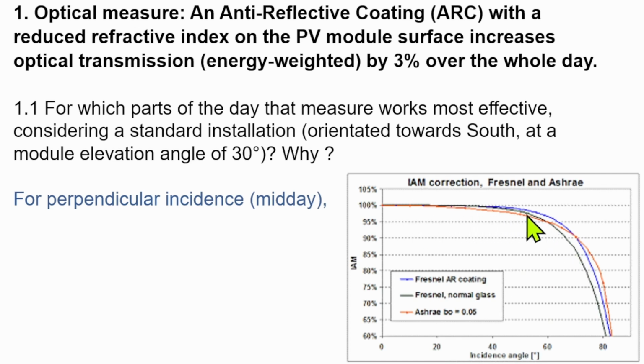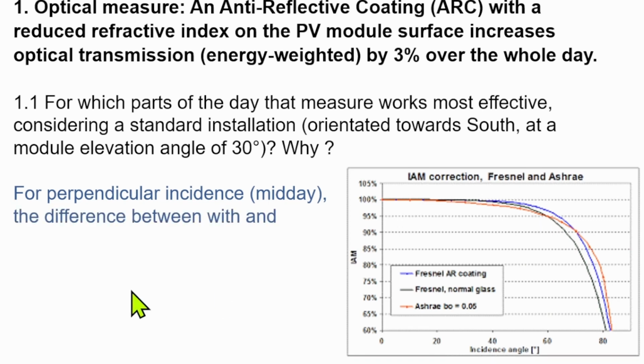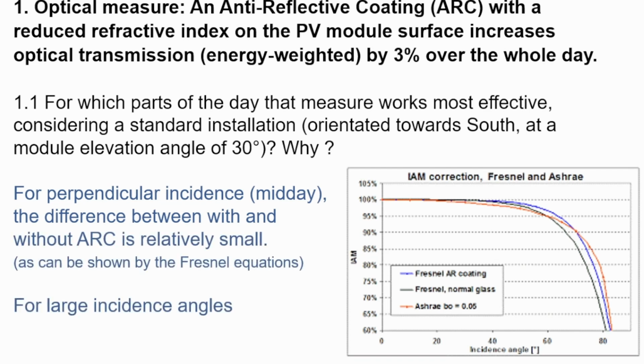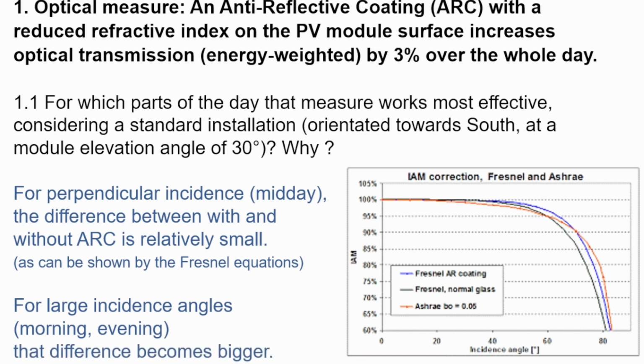So here you see the effect of the anti-reflective coating. So you don't see such a big difference at perpendicular incidence, but more at higher incidence angles. You can also calculate it mathematically by applying the Fresnel formula. So for larger incidence angles in the morning and evening, the difference becomes bigger.